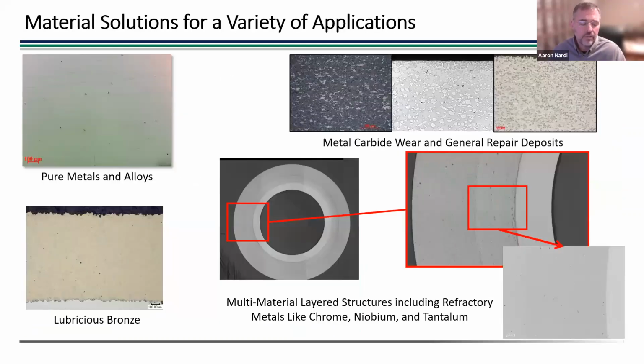So as I said, there's a wide variety of materials that you can process. So we do metals and alloys, we do blends. Metal carbide blends are really popular, especially for wear applications. Bronzes with wear phases or lubricious phases. And then you can create all kinds of structures because you don't have to worry so much about melting and metallurgical incompatibilities and things of that sort. So you can put layered structures together that could be very complex. This is just an example of a three-layer refractory material.